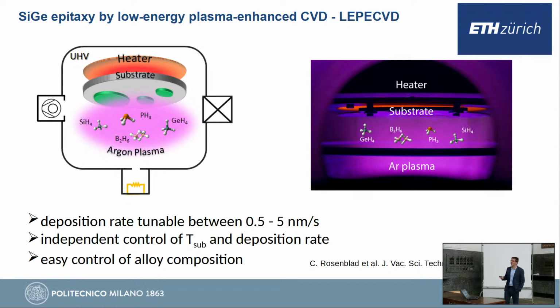What's happening inside is the following, essentially. So we have a plasma source, which is simply a hot filament which emits electrons. These electrons are accelerated in the main chamber, and this plasma is sustained by an argon discharge. So this is very similar to neon tube discharge. It's a DC current. And then we let in our precursor gases, silane, germane, and then we have molecules containing boron and phosphorus for the P and N-type doping. And these molecules are ionized, or in many cases just excited by the impact with the electrons of the plasma. So they become reactive, and when they hit the hot surface of a sample, they basically stick to it in an epitaxial manner. So you maintain the order of the underlying substrate, and you obtain crystalline materials.